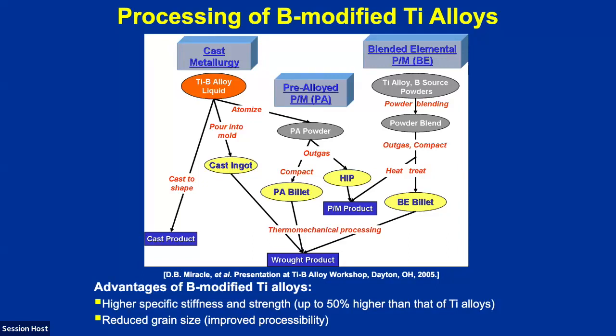And the trick is this: because it's an inoculant, when you put it in a casting and you cast it, you can get significantly reduced grain size, orders of magnitude smaller than you would without the 1% or 0.1% boron. The trick is to add the amount of boron that you want in the material for the performance that you want. The more boron you put in there, the more the ductility will decrease, but you get higher strength and higher stiffness.